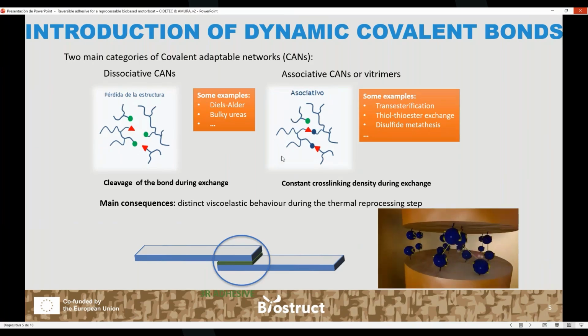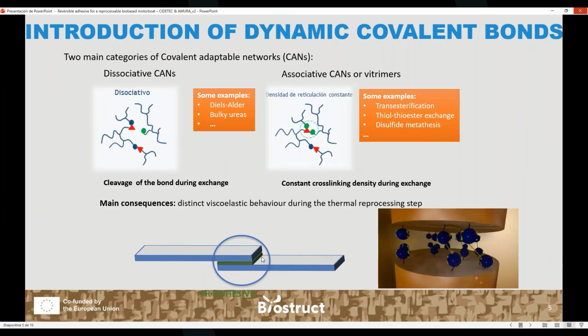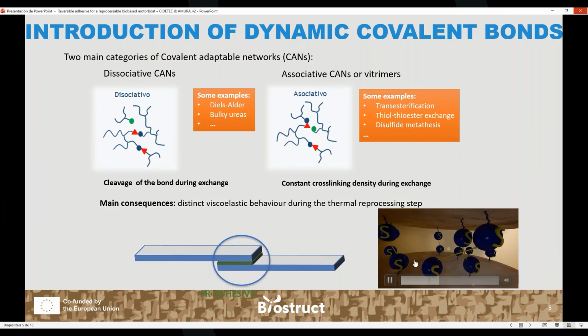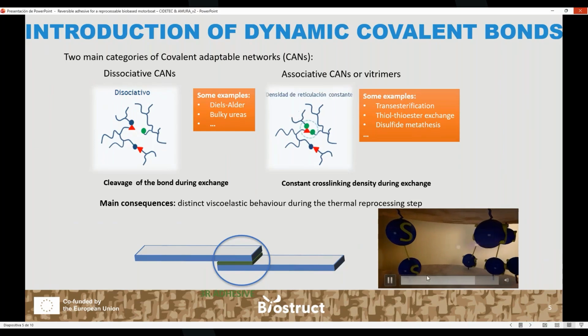you can see what occurs within this debondable adhesive layer when we heat the material. As you can see, we don't cross-link the material. What we obtain is an exchange between these disulfide bonds, allowing this easy dismantling of bonded parts.